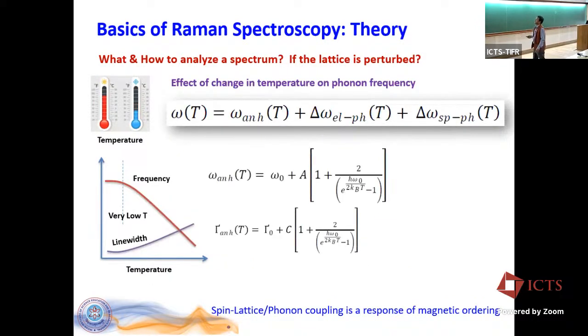All right, so let's say we are using temperature as the variable, and we're looking at how the frequencies would change as a function of temperature. These are the possible effects which can be incorporated in the overall frequency change due to the temperature change. So one is certainly the anharmonicity, which I mentioned, and it will behave in this form. But apart from that, if the system has electron-phonon coupling, there will be some contribution from that. If the system has spin-phonon coupling, then it also has some contribution. So because of these contributions, there will be a deviation from the behavior due to the anharmonicity. That's what we try to capture.